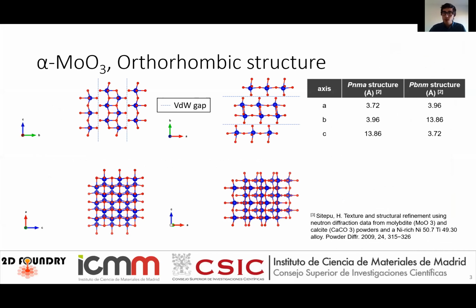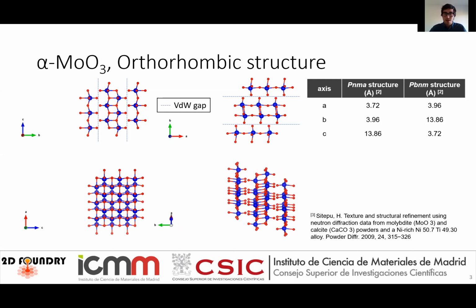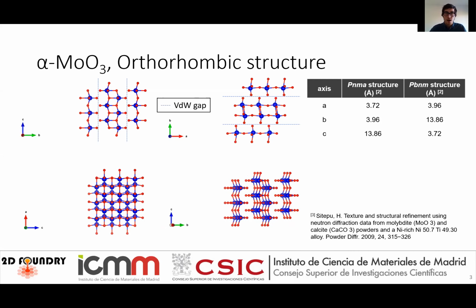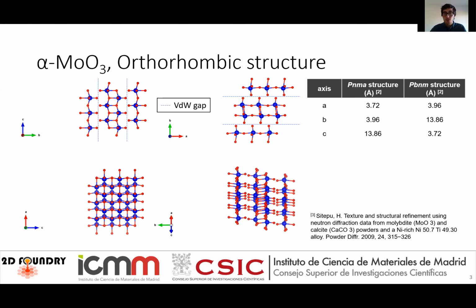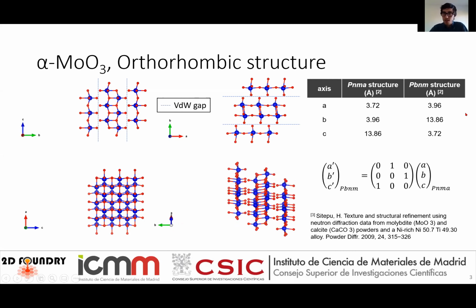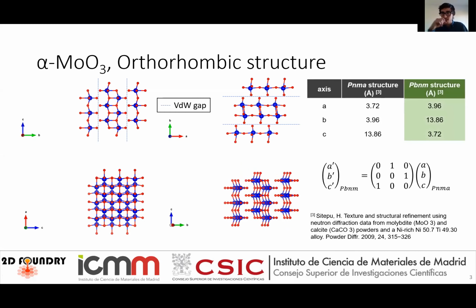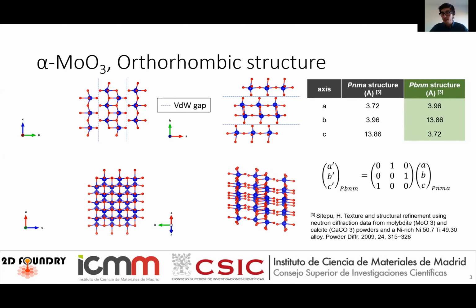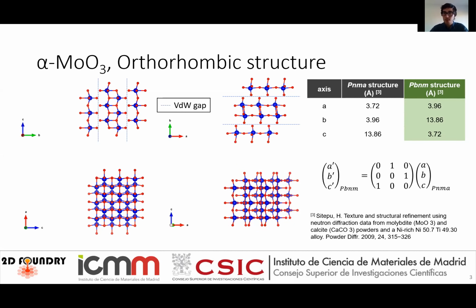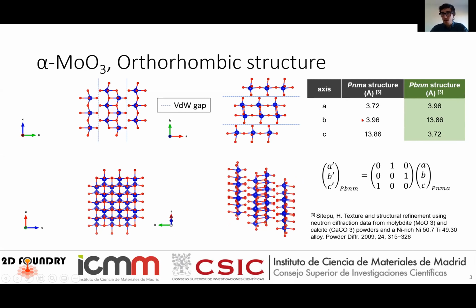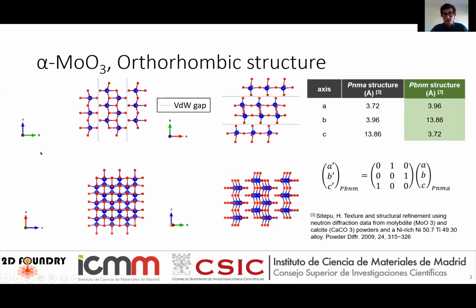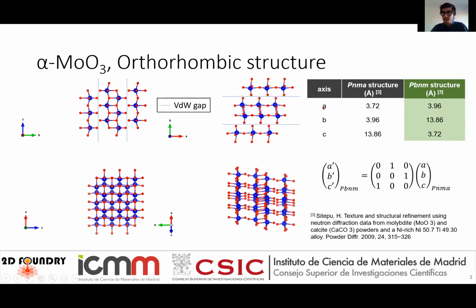But what we are really interested in right now is its structure. Since it's a van der Waals layered material, it has a direction in which atoms are more separated, and it also has in-plane anisotropy. For this space group you can get two types of notation, the Pnma or the Pbnm. These two are really the same, but with a rotation matrix. And we use this one, in which we place the b-axis perpendicular to the van der Waals gap, the shorter direction we set as the c-axis, and the longer direction is the a-axis.